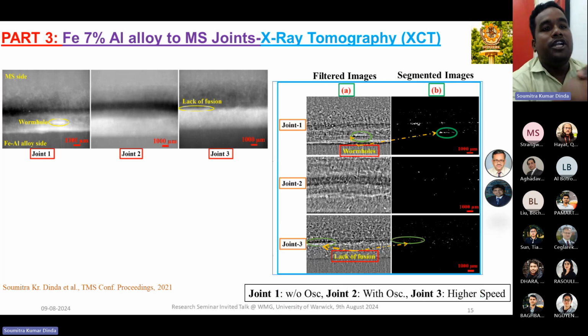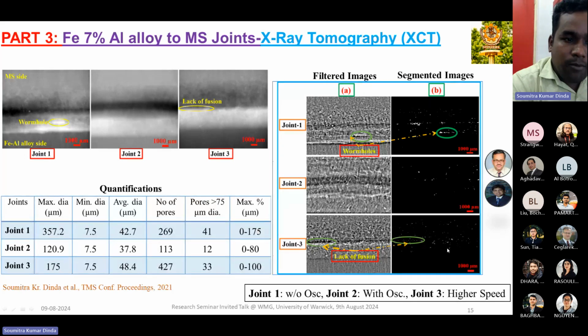Then we did some image analysis, performed with image software. We did background subtraction, image filtering, and thresholding, everything. After segmenting the image, we get some results, and this is the quantified result. But everybody should understand that this image analysis is not good for quantitative data. Instead, we can perform this study to get the trend of our results.